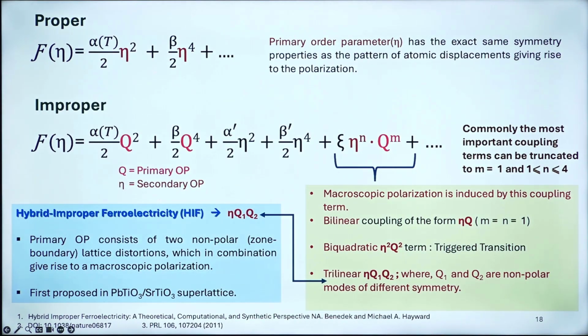In a proper ferroelectric only one parameter is involved, but here it is more than one, which we can write in the free energy expression. You can see the primary order parameter is eta here, so it is quadratic. But when you discuss the improper case, you have a term with primary Q as well as this order parameter eta, which is the secondary order parameter. Both are involved, and then you have a dot product of this, and this will have a combination, and you can expect the phonon modes to be imaginary or soft at any other point other than the gamma point also. It can be at multiple points, and it can be continuous along the Brillouin zone also.